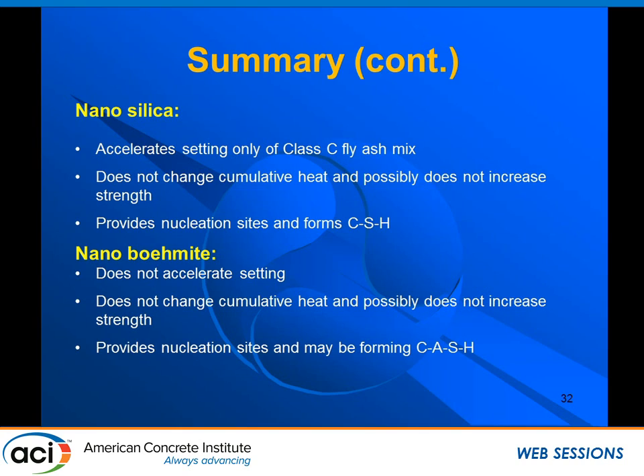For neither of the ashes that we tested did it improve the cumulative heat, so we don't think it will improve the strength. It does provide a nucleation site for the formation of CSH.